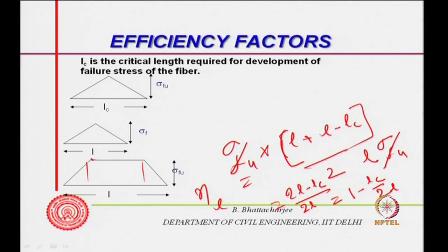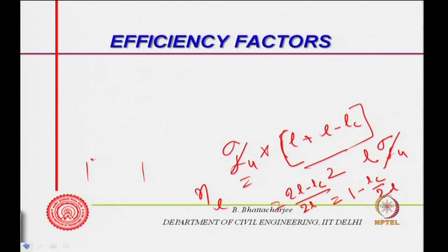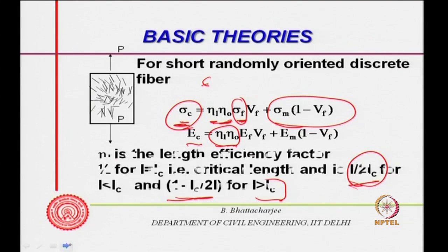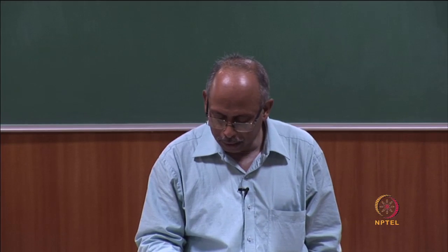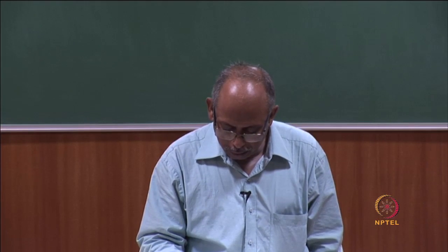So, that is the length efficiency factor, and that is what we have seen earlier in the previous slide. We have seen that it is 1 minus L C divided by 2L if L is greater than L C. All right.